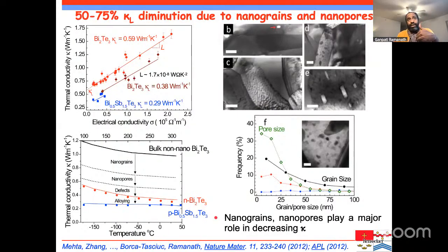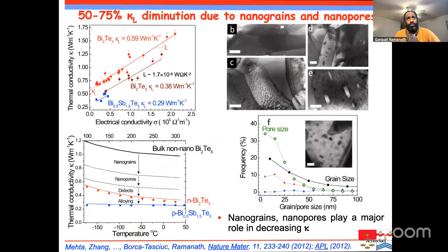And here is the kappa decrease. We know the Wiedemann-Franz law: thermal conductivity and electrical conductivity are correlated. Now, when you decrease the grain size or the pore size, you're able to get low kappa. So this is actually well known.